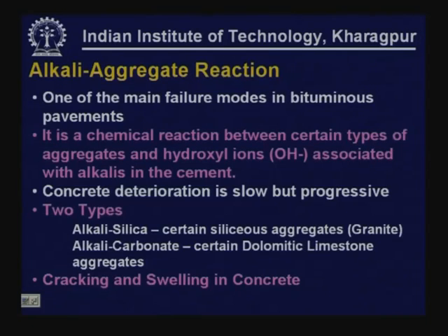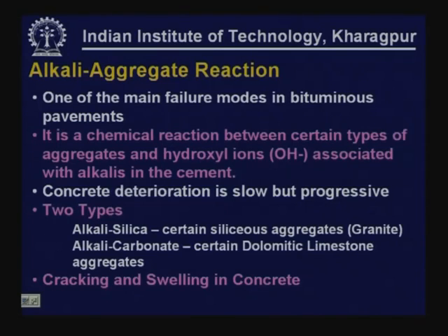Alkali-aggregate reaction is a chemical reaction between certain types of aggregates and the hydroxyl ions associated with alkalis in the cement, causing slow but progressive concrete deterioration. There are two types: alkali-silica reaction, in which siliceous aggregates such as granite are susceptible, and alkali-carbonate reaction, to which certain dolomitic aggregates such as limestone are susceptible. This results in cracking and swelling in cement concrete.